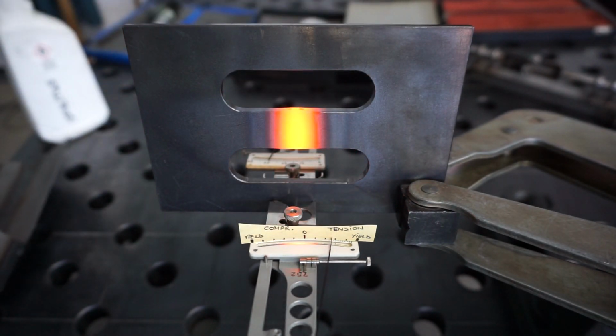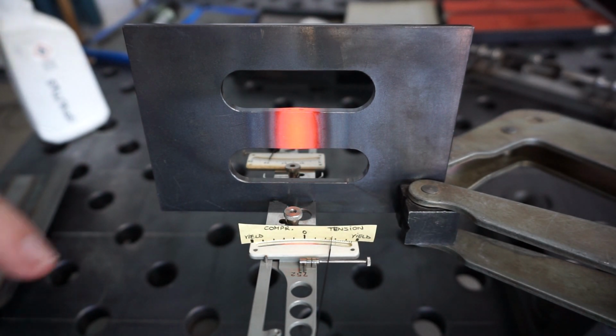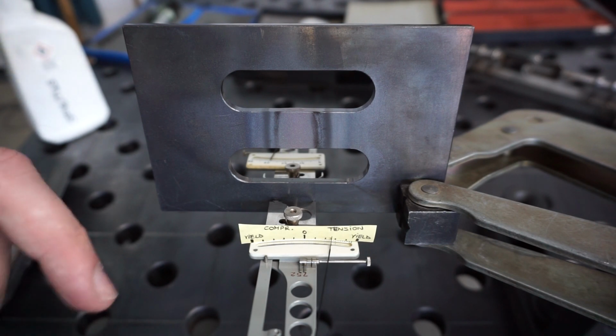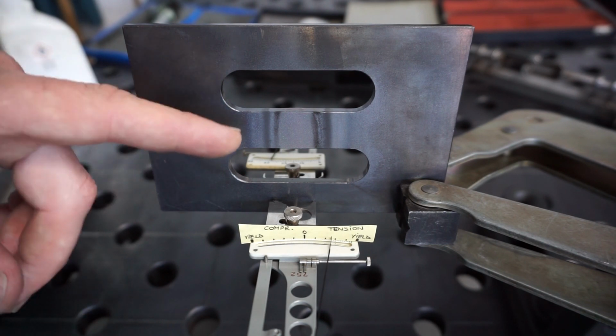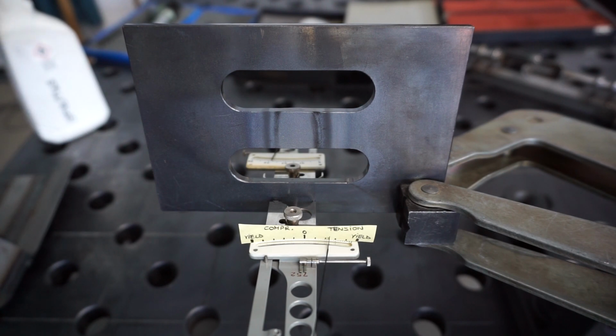I have now heated the central bar to an orange red, and our maximum reading on the outer bars is approximately almost 60% of the yield strength of the material. This in turn means, times two, that the central bar is loaded with almost 100%, or a bit more than 100%, of the yield strength of the material. So obviously this material has a little more strength than in the data sheet, but nonetheless.